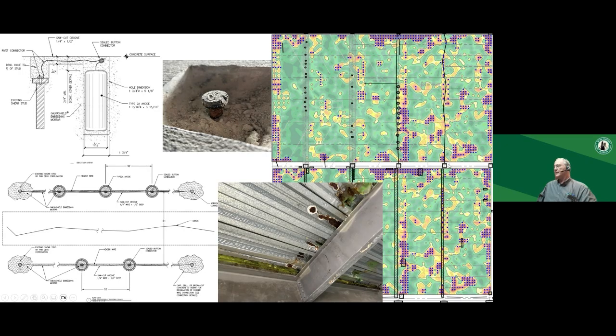Here's a project. You can see the cracks. This map is a heat map where you look at the corrosion potential, and these little square dots are where you would put a targeted anode, one of those drilled-in anodes. What we're doing is looking through the concrete at the metal pan, and we're saying, oh, there's corrosion in this area of the metal pan. You'll see this crack. The surface doesn't look bad, but underneath there is corrosion in the metal pan. And all these little bigger dots right here, those are your studs, your shear studs.